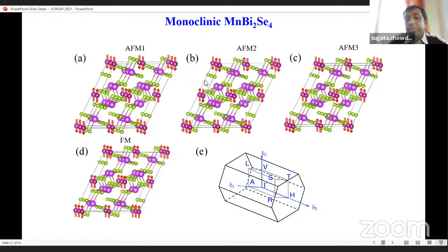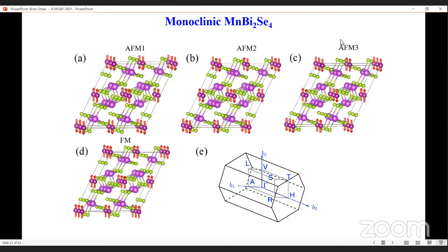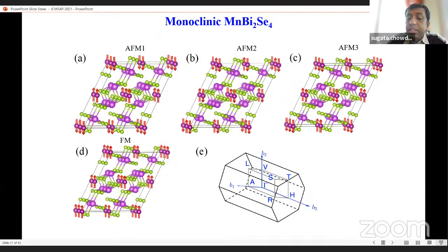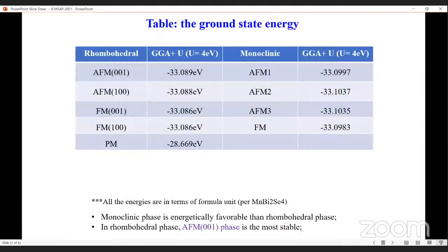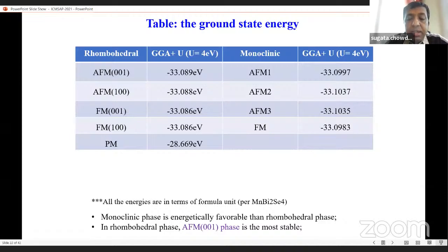Here he considered three different antiferromagnetic configurations. You notice this layer is completely up and this layer is completely down, but here it alternates. Similarly, it is column-wise, this is column-wise, this is column-wise, so three different configurations were actually considered in this case to understand the monoclinic structure, because the monoclinic structure is actually the ground state for the magnetic system, and in single crystals it forms naturally. So he found energetically it matches our previous result that the monoclinic phase is energetically favored over the rhombohedral phase.